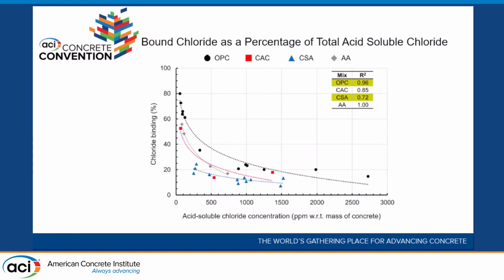We started to look at what's going on here a little bit. So we looked at how much of the chloride was water soluble and how much was not, from the acid soluble range. We can see that for the OPC, at relatively low chloride contents, most of the chloride is bound. As you go farther out to a very high chloride content, at the right-hand side, you've absorbed all the chloride that you can on the cementitious phases, so most of it is now going to be in the pore water solution. You can see that the CSA samples, the blue lines on the bottom, were a little bit lower. They do not bind as much chloride as is bound by the other phases. It's probably because there's no C3A in that, which is known to combine with chlorides. So that's an important feature.